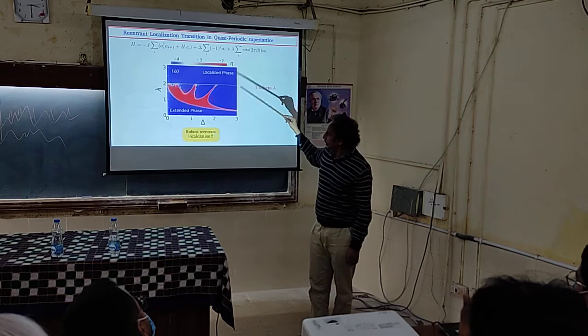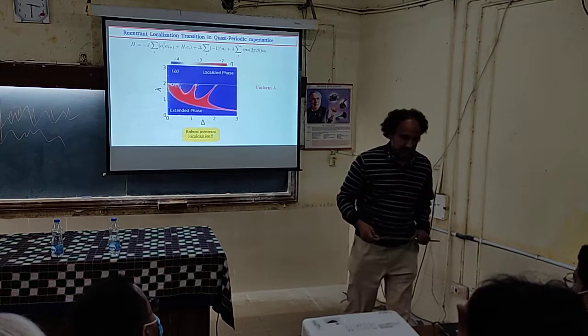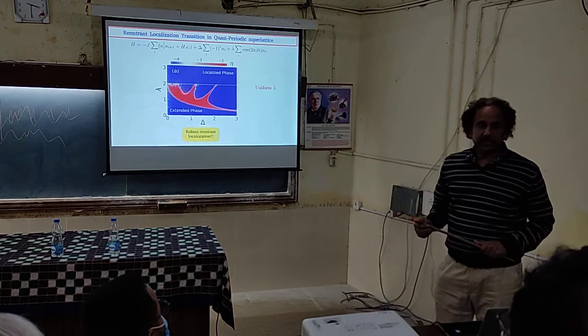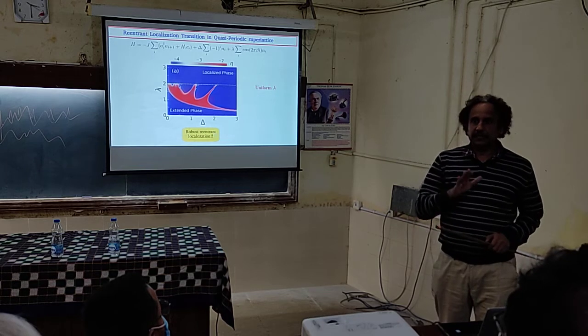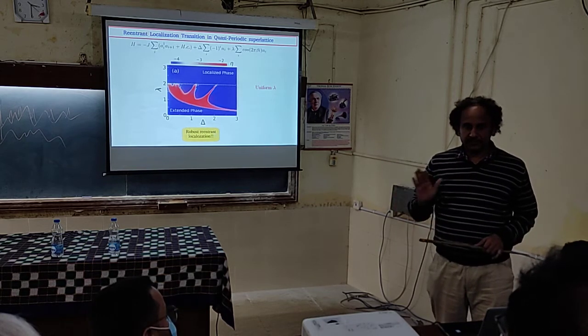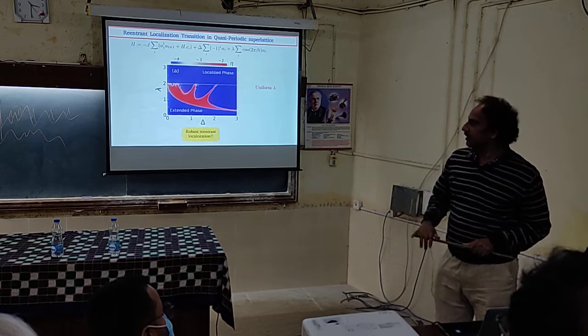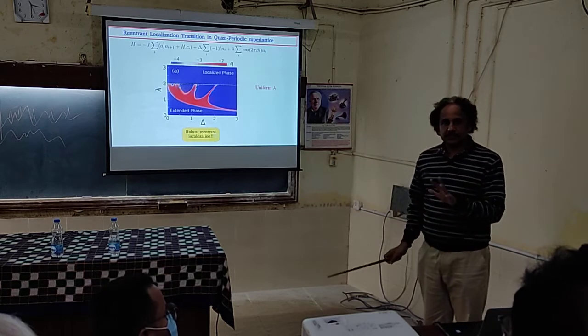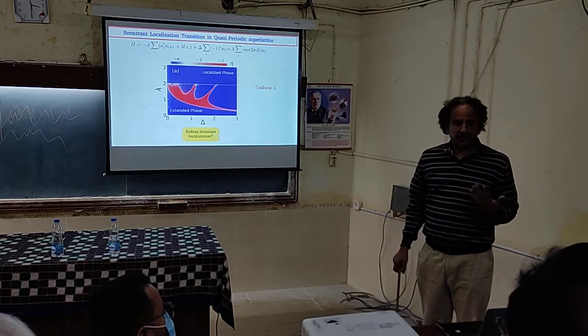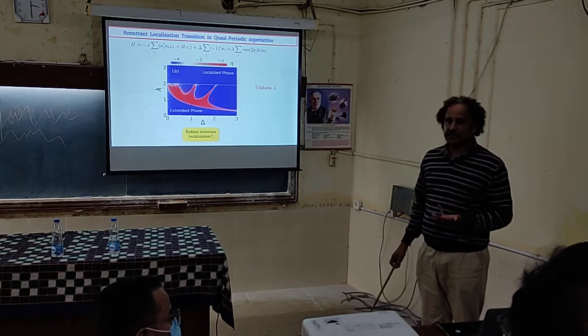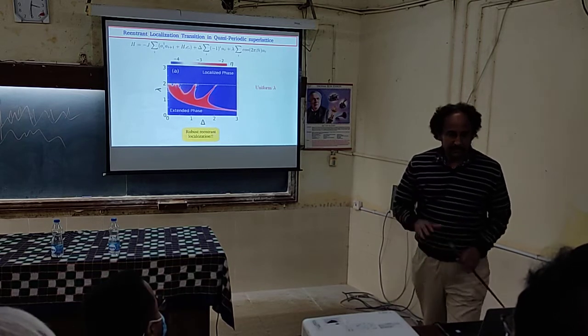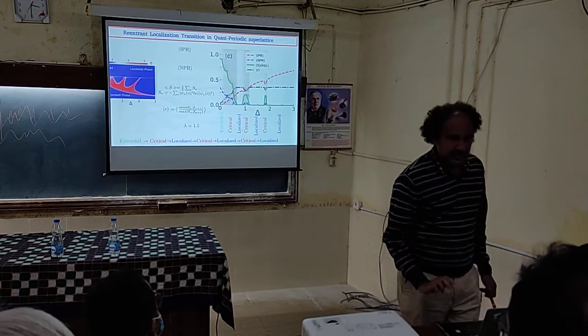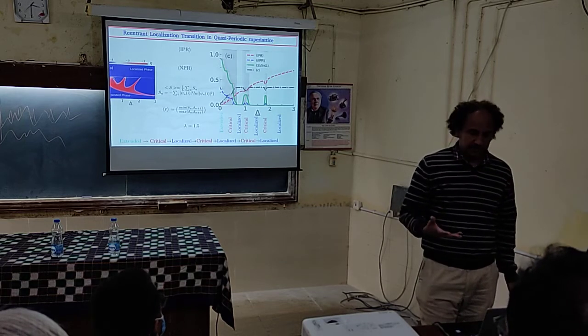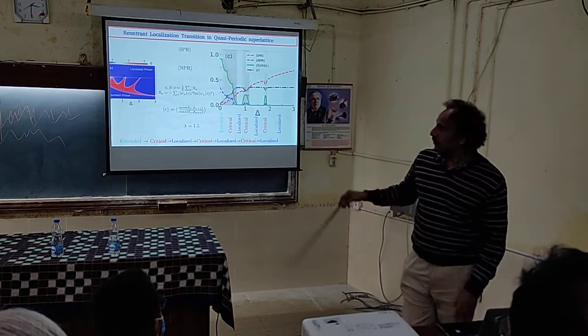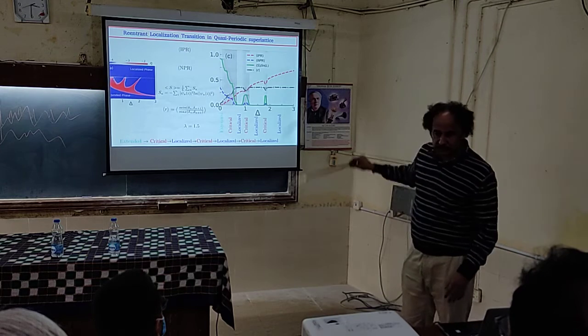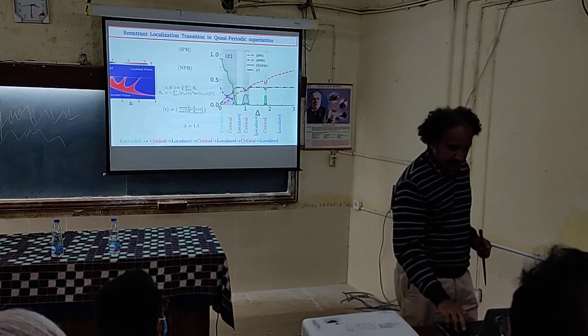So this completely contradicts the earlier understanding that the system remains localized forever if you increase the disorder strength. But here we are showing that the system can go through localization and delocalization multiple times. Okay? So this is a very simple model, and this can be experimentally observed because it's very simple. I will not go into the details of the order parameter that we use to compute this phase diagram.